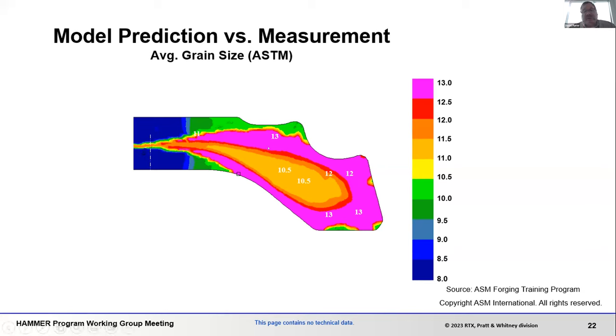And it turns out that there's another region that also forms, shown here like a teardrop shape. It is producing a region of around ASTM 10 grain size, which is about 10 microns, and that is due to adiabatic heating. So we have had enough strain in this part. We've dynamically recrystallized the majority of the part. We've dynamically recrystallized this region here as well, but we had enough adiabatic heating to cause grain growth. We've been able to actually predict it. This is a predicted contour, and it matches almost spot on with measurements as well.